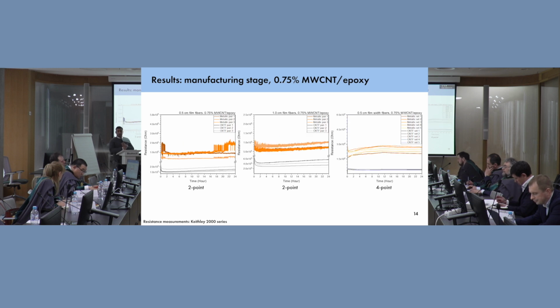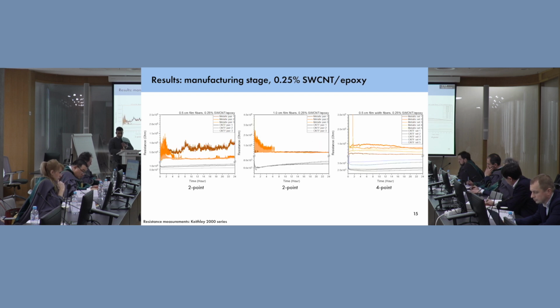So we continue this range of experimentation with a higher weight percentage. And again, we see the same typical type of behavior, higher magnitudes for the metallic embedded electrodes. We see higher noise as well during this whole curing process. But as soon as we switch to 4-point, for the metallic electrodes, these measurement errors are removed, but for our carbon nanotube fibers, we still have very stable results which match between the batches.